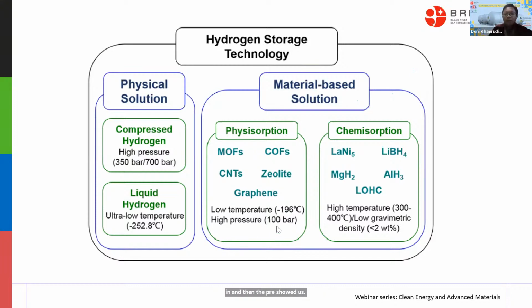Therefore, the DOE requirement, if possible, is less than 20, less than 30 maybe, if possible. Okay, however, 100 bar is not so high compared with 350 and 700 bar. There are still many compressors, even in our country, Indonesia, that can operate at this condition for sure.